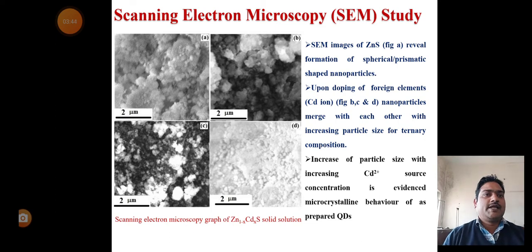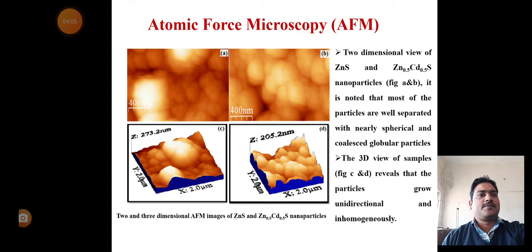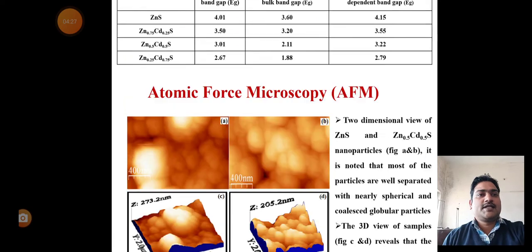Scanning electron microscopy images of as-synthesized ZnS reveal formation of spherical prismatic shaped nanoparticles, and doping of cadmium and nanoparticles merge with each other with increasing particle size for ternary compositions. In the atomic force microscopy two-dimensional view of zinc sulfide and zinc cadmium sulfide nanoparticles, it is noted that most of the particles are well separated with nearly spherical and coalesced globular particles. The three-dimensional view of samples reveals that the particles grow unidirectionally and inhomogeneously.